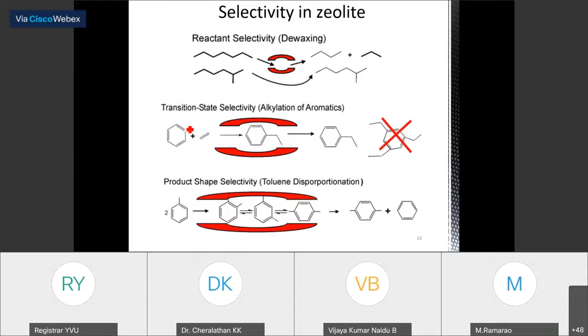And not only that, it can even exhibit transition state selectivity. For example, in the alkylation of aromatics, there is a possibility that the benzene ring will be alkylated in multiple positions. In normal conditions, if you perform the reaction in a liquid state, in a beaker, what will happen? In multiple positions, it will be alkylated as shown here. But if you perform the same reaction on a specific zeolite, selectively you can have a monoalkylated benzene. It is happening because of the restricted transition state, which is formed inside the micropores of the zeolite.